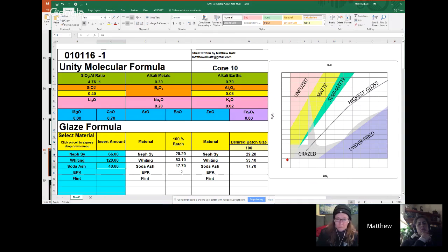To a certain degree, actually, the cool thing is that there's so much sodium, you're actually going to saturate the water in your glaze anyway. So it makes it so that you can use the soda ash to do something crazy. But now, Chiara, you're going to hit a real problem with trying to go to cone 6, because the soda ash could very potentially react with your boron sources and make a borax crystal in the water of your glaze. And that's a huge problem because it's a super hard crystal. They're really big, and you really can't get rid of them. But compositionally, this totally works. It's got studio problems, but it can do awesome things because we're all the way down here.